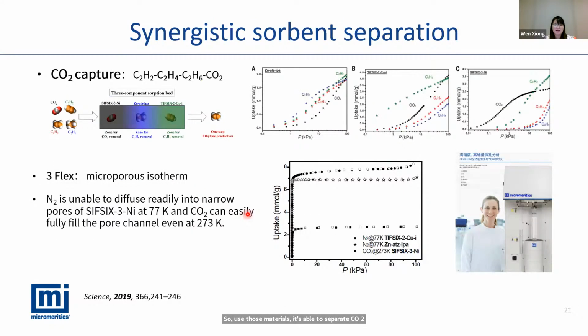As I mentioned earlier, our 3Flex has superior micropore performance for high-end research in emerging materials for adsorption. For the customer's materials, the nitrogen is unable to diffuse into those narrow pores in the materials. So they instead used CO2 for the testing. CO2 can very easily go into the pore channels, even at high temperature compared to the liquid nitrogen temperature. So here I'm happy to show an example of using our 3Flex to check the micropores, especially the very narrow small pores, structure and adsorption mechanism.